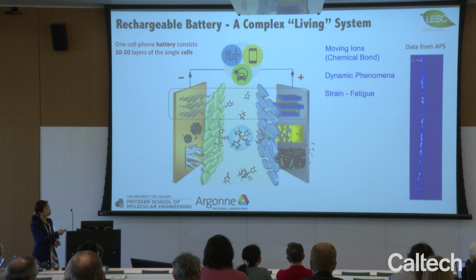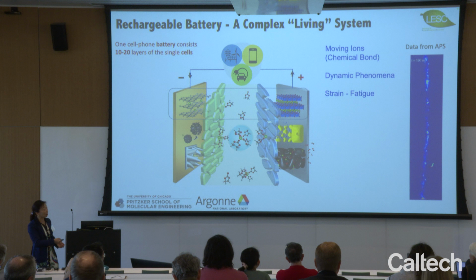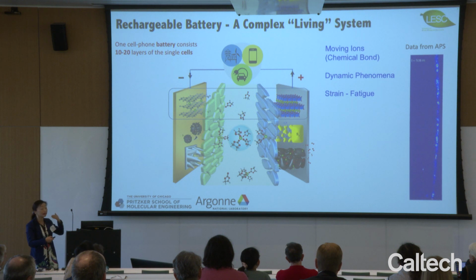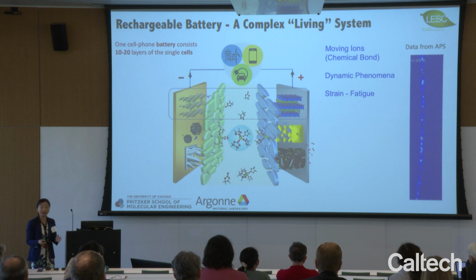But even within the intercalation compounds, we took an approach at Argonne National Laboratory using synchrotron to observe batteries while they are operating. So in the highly coherent X-ray, you can actually capture many, many particles, how they transit with the electrochemical signals. And then during the discharge, you can see phase changes, volume changes, and the process is completely reversible in functional batteries. And this process has to repeat thousands of cycles.